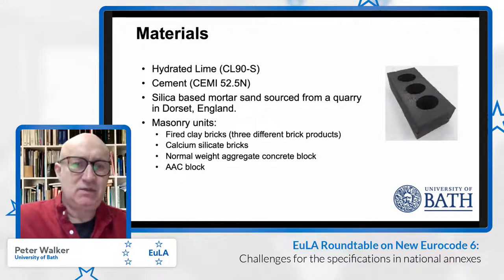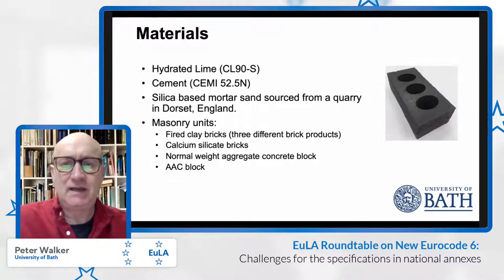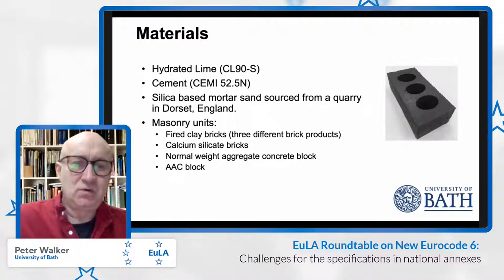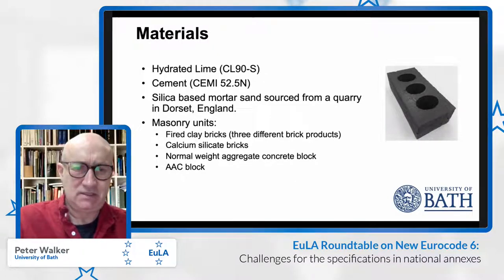And so some of the materials we use, we use hydrated lime. We use CEM I 52.5N cement. We use one type of silica-based sand from a quarry in southern England, which is a widely used, established sand for mortars, and was compliant with the grading requirements. And we also looked at a variety of masonry units, fired clay bricks, mainly perforated, such as the one you see in the photograph there in the slide. We used three different fired clay bricks with what we broadly term as high, medium, and low water absorption characteristics. As we know from previous research, the water absorption characteristics of fired clay bricks have a significant effect on masonry properties and on the bond between the masonry unit and the mortar.